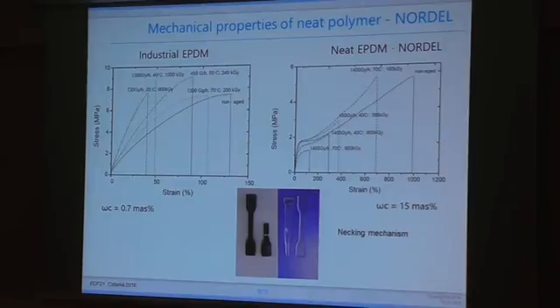First of all, when we did the tensile test, we noticed the first main difference in the stress-strain curve. We can see that the neat polymer elongates almost up to 1000%, while our industrial polymer goes only up to 130%. This is expected because our industrial polymer has a lot of additives that decrease the elongation properties. The second point is that we can observe a yield point in the stress-strain curve. This yield point is observed because of the crystallinity present in the neat polymer, and it is much reduced in the industrial polymer, again because industrial polymer has a lot of additives that prevent polymer crystallization.